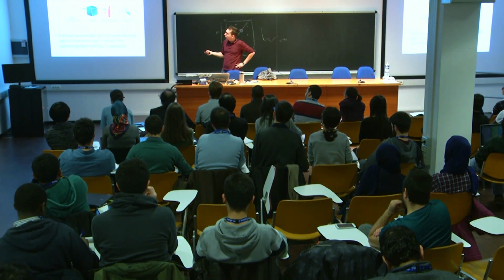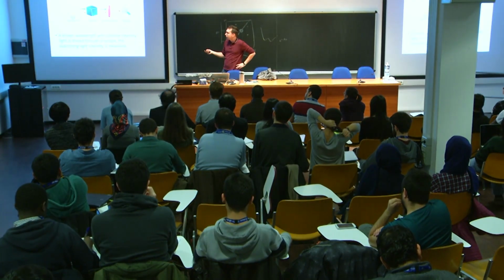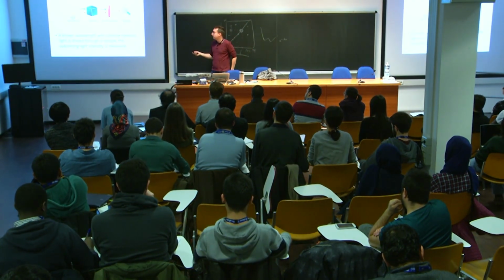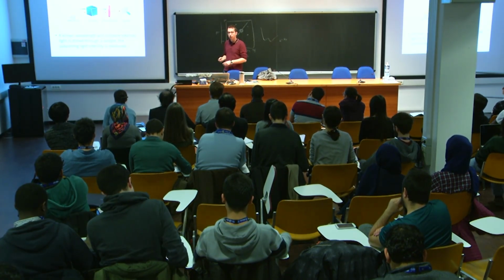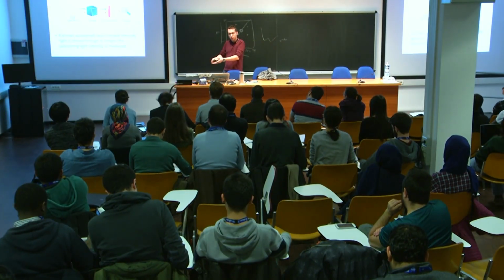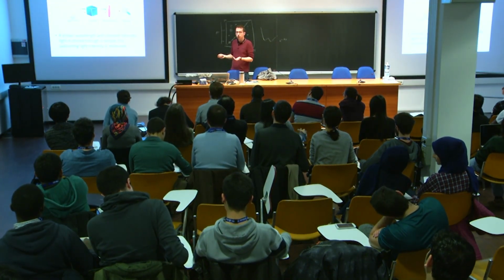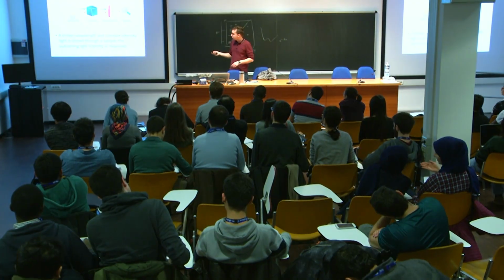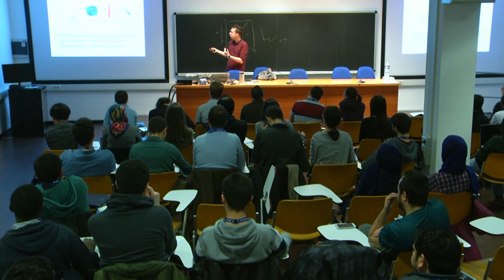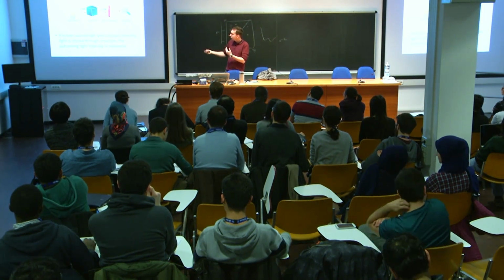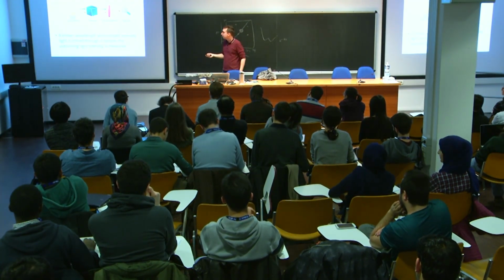What is important, and I'm only going to talk a little while, is if your sample is molecules, like molecules in a gas, then everything is disordered, or it could be a liquid, or it could be a powder. Often the sample is not a perfect crystal, but a kind of powder, and it doesn't have really a macroscopic order. So in this case, the polarization of the light does not really matter. But if you have a nice crystal, then you can try to polarize the light and measure the polarization. The outcoming light is also polarized, in the same direction or in another direction, and this can give you more information.